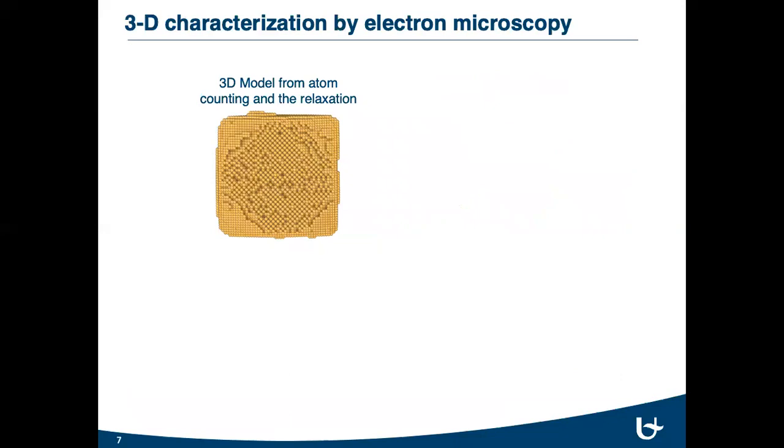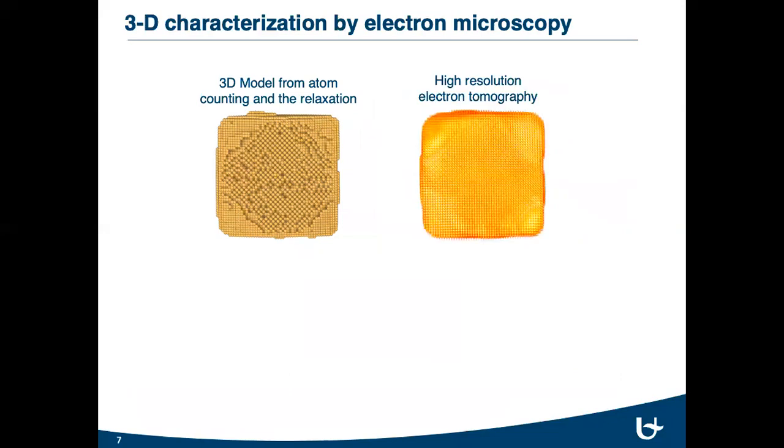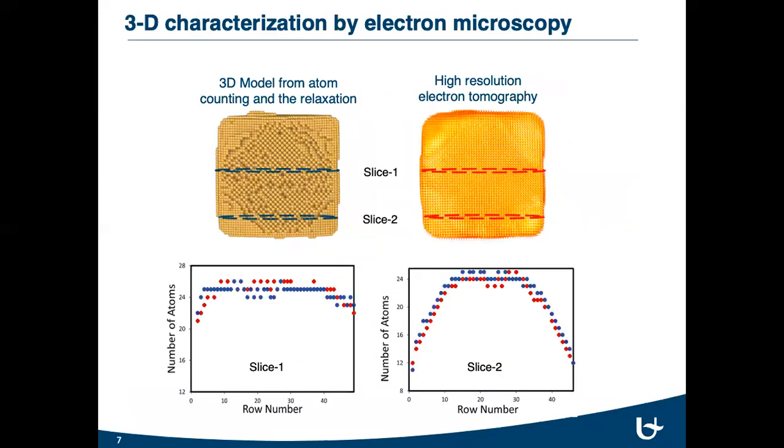So, as an alternative method, atom counting is combined with relaxation studies to obtain the three-dimensional model. For the validation, this reconstruction is compared with the high-resolution electron tomography from different slices. According to the total number of atoms at each slice, it can be seen that there is a great match between these two methods. And this shows the reliability of the alternative approach.